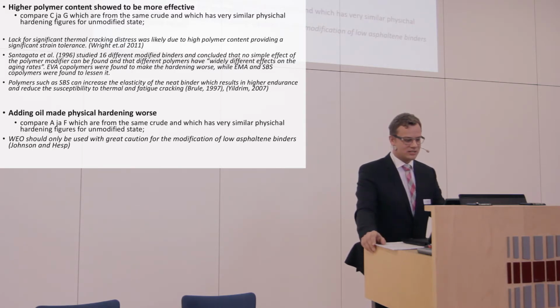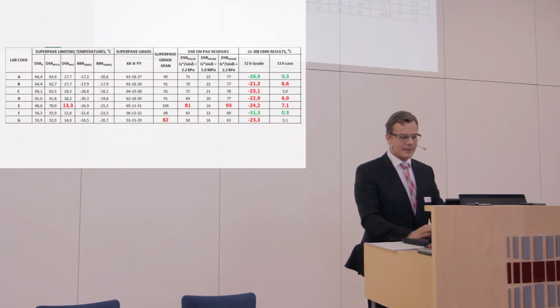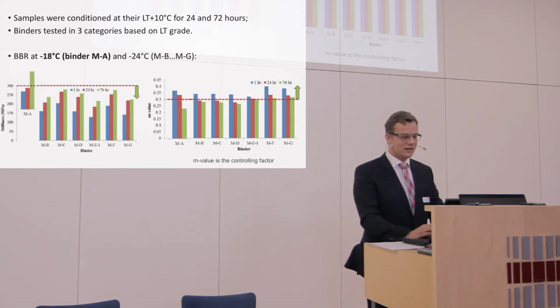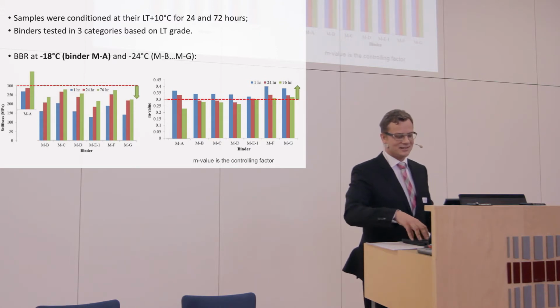Also, our results show that adding oil made physical hardening worse. When we compare bitumen A and F, they are from the same crude and have very similar physical hardening figures for unmodified state. Neat binders don't suffer at all from physical hardening, or don't have any grade loss. But when we add oil inside it, for 72 hours conditioning, physical hardening goes up to a very high level, and it shouldn't exceed this red line, and it does exceed this red line. It shows that there will be some very bad physical hardening happening inside it.